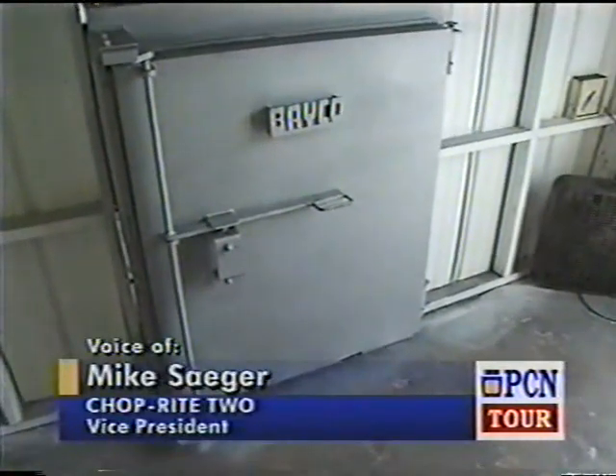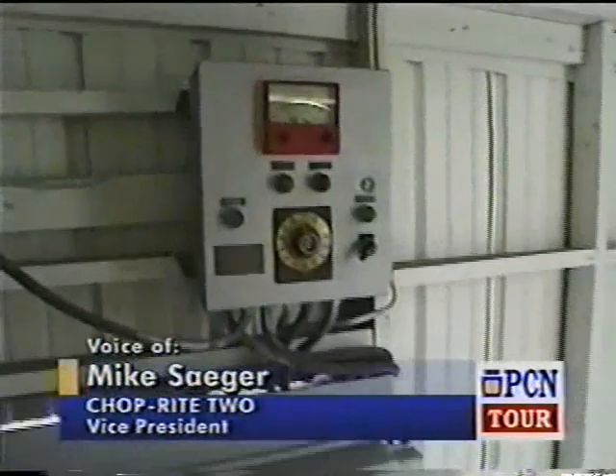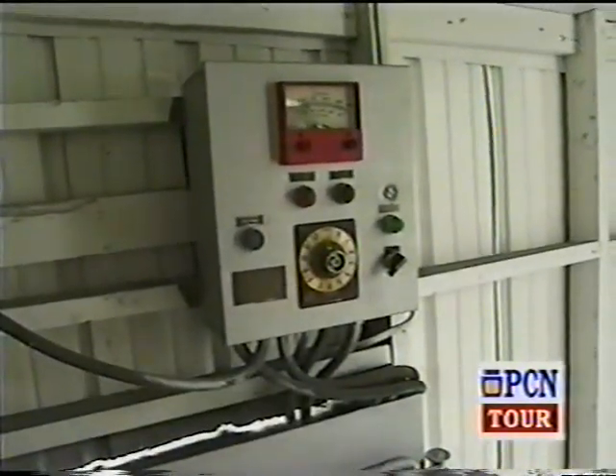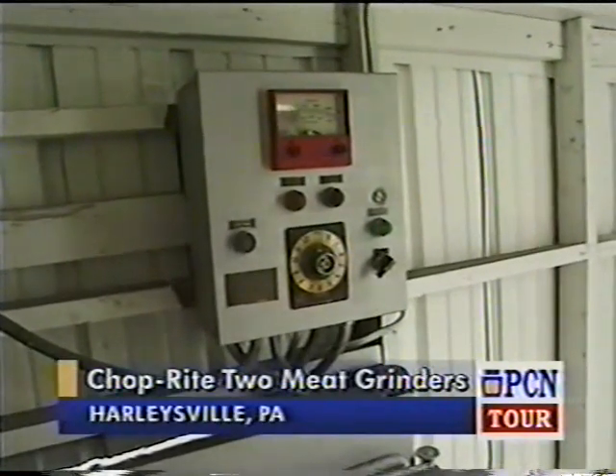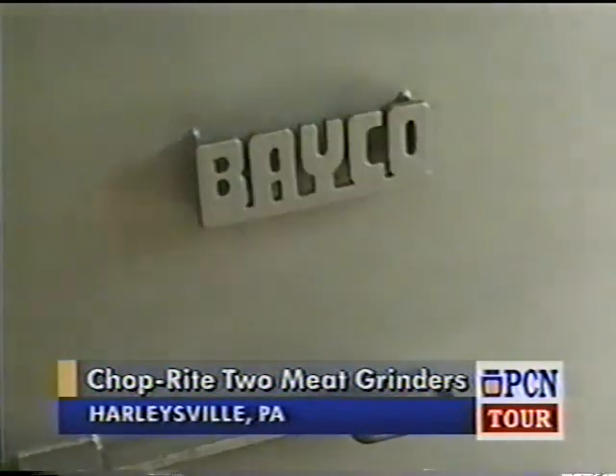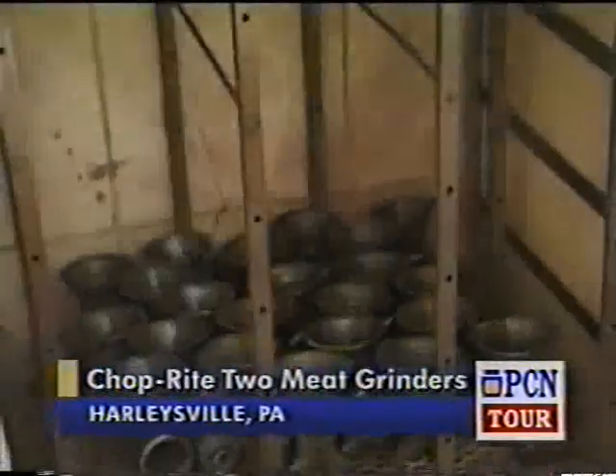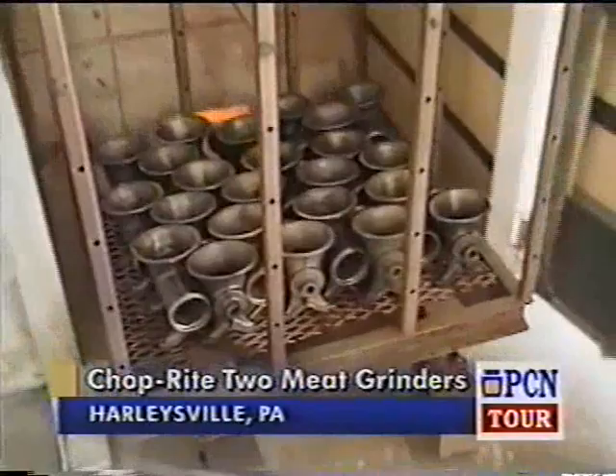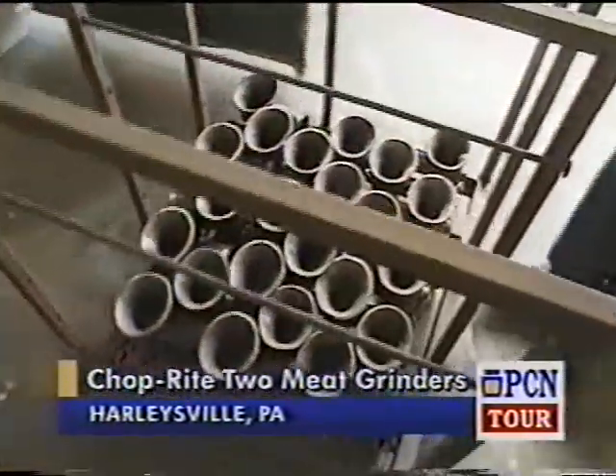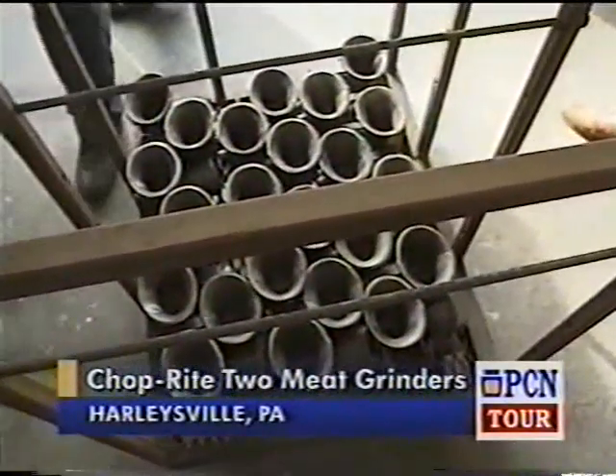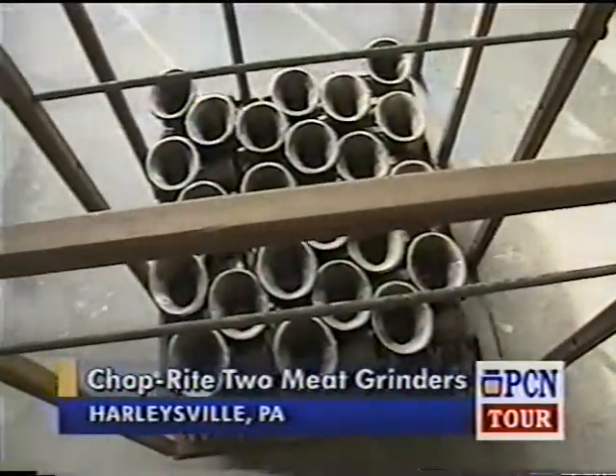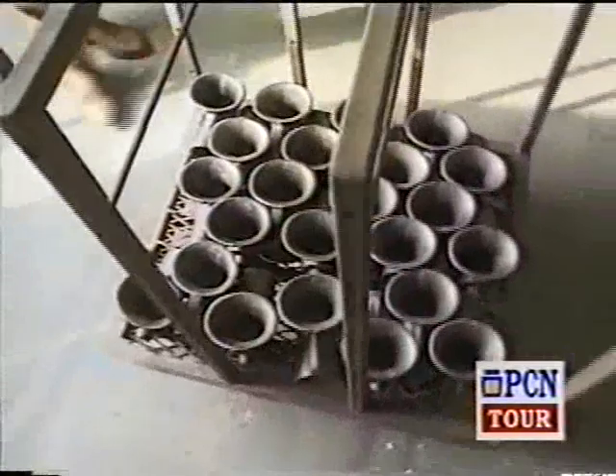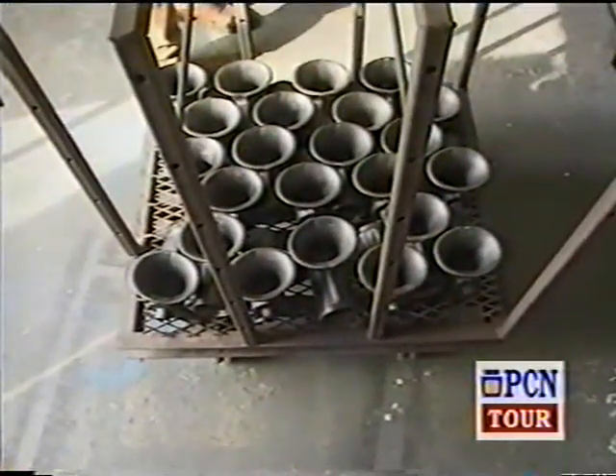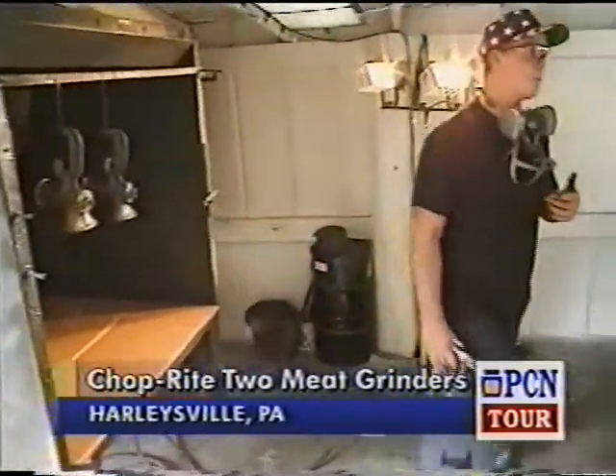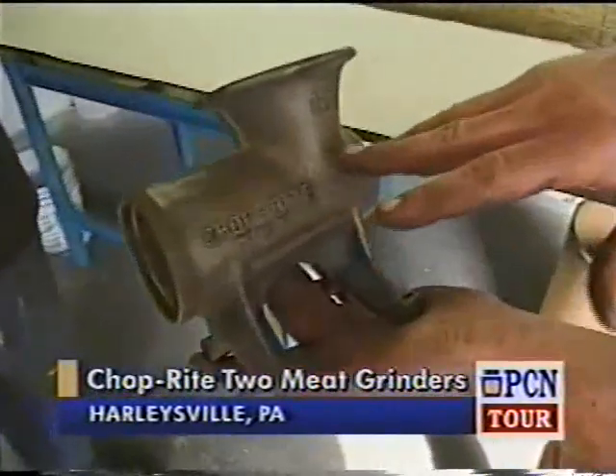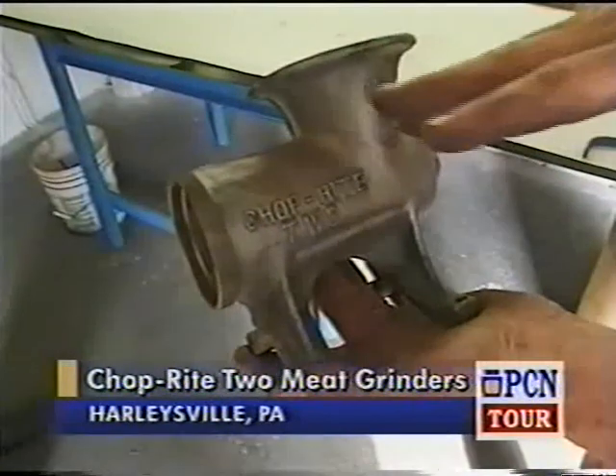The oven's set at 400 degrees within 10 degrees fluctuation. And these will be baked for roughly 20 minutes. After 20 minutes are up, we open up the oven, we bring out the castings. Here he lets them cool down to room temperature and then he'll coat them. You can see the color of the casting when it comes out of the oven, how it's not just gray colored anymore. It has light spots and dark spots.